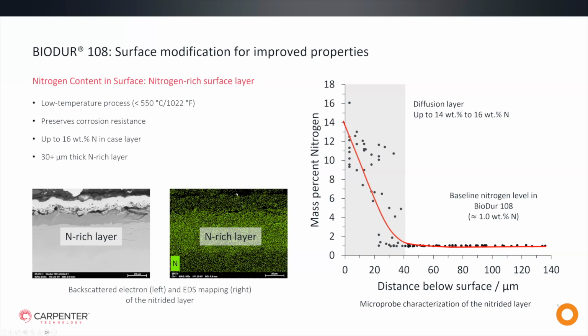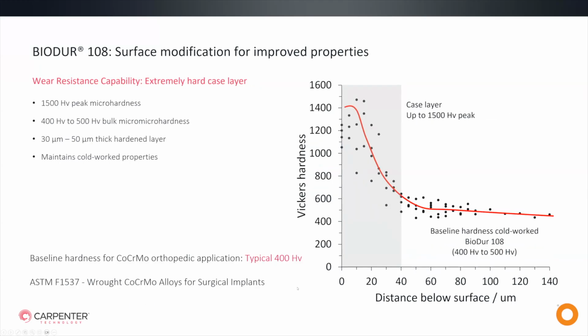Beyond the imagery I just showed that was somewhat simple in the last slide, we also tested nitrogen content for the nitrogen-rich layer. And what we found is really what you may expect, right? We had elevated nitrogen levels up to 30 plus microns, driving deep penetration of this extreme wear-resistant skin. The nitrogen layer not only increases the wear resistance, but further supports the austenitic structure of the base alloy and really contributes and preserves the corrosion resistance of that austenitic base material.